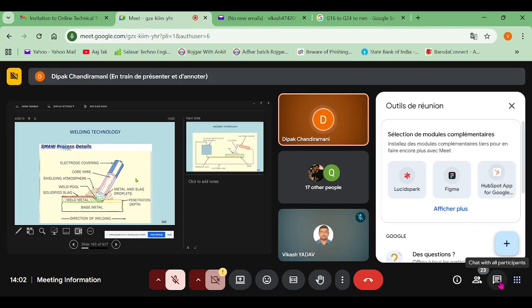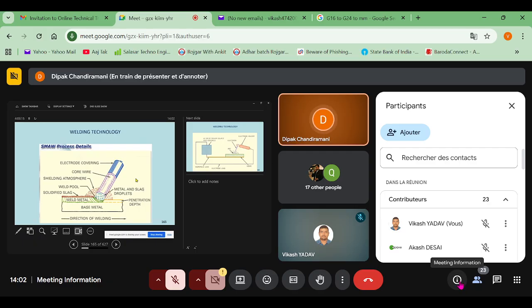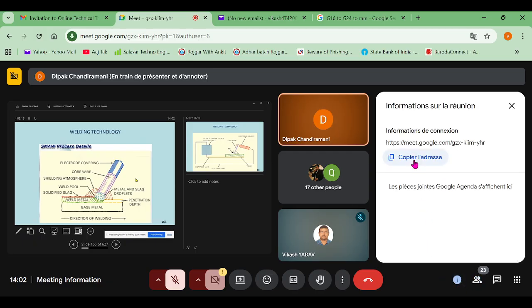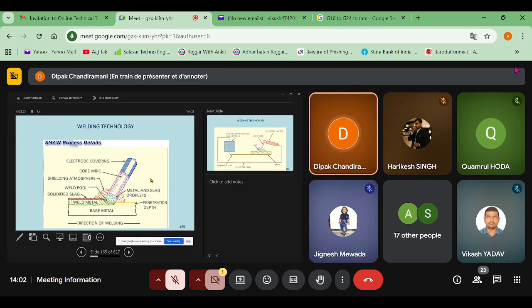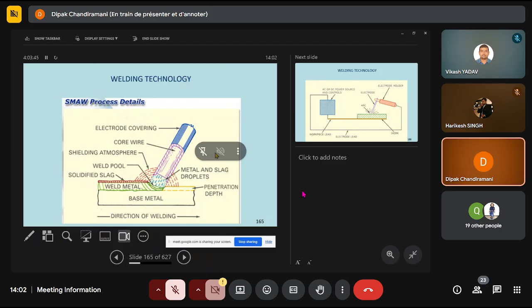And like that, we proceed getting into the, this is your depth of penetration because we have some amount it will go in. We don't really care how much it goes in because we want surface melting. Once the surface is melted, it will join. But this is a consequence. We cannot stop at the surface, so it will go some depth below, and then you will have something called dilution. That means this metal's chemistry will mix with this chemistry and make net chemistry, which is something which can be calculated, of course. Those things are important in stainless steel typically to get the proper microstructures.